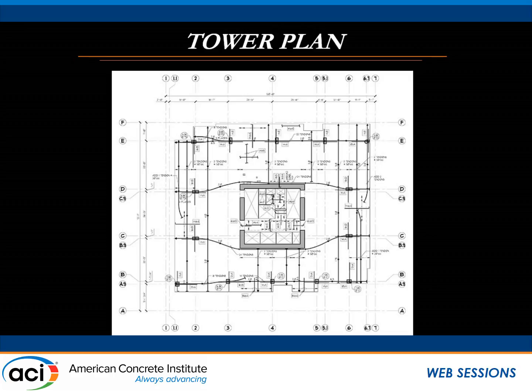We stubbed the anchors at the edge of the core because the core was self-climbed on the parking levels, and then it was poured floor by floor with the slabs. So on the parking levels, you didn't have any sandwich of the slab in here. On the upper levels you did, but the core itself was only 8,000 psi anyway. So these are the cantilevers. You can see some of these dimensions here. This is one of the worst on this side right here. This is a column wandering at the edge, and this column right here was 15,000 psi on the lower level. It's almost a corner column, and that's why we had to do this stay-form system.